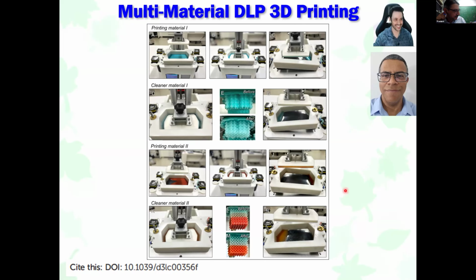Our aim was to use a kind of commercial printer, where we just modified the tank, the vat of the resin, to get this kind of inclination. So we have a tilt of the vat here. We can introduce one material, print the layers with this material, tilt the vat, and remove the material. We don't want to throw it away, so we recover the material to the original tank. Wash the tank, insert the new material, and these steps are repeated for any layers of different materials you want.